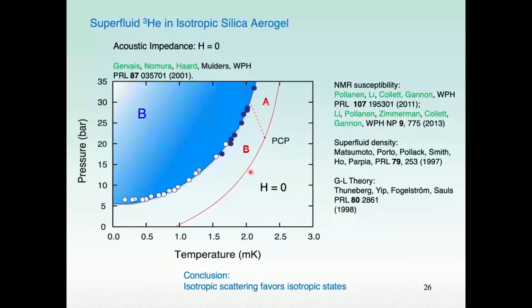But it's interesting already to note that there's no A phase window up here. And that's in part because there's a suppression of the transition temperature by some amount, not a lot, but a significant amount. And as I had mentioned before, that strong coupling is reduced as you reduce the temperature. And so therefore, the A phase, which exists in pure helium-3 as a consequence of this strong coupling, that's gone. And so what you're left with is just the B phase.